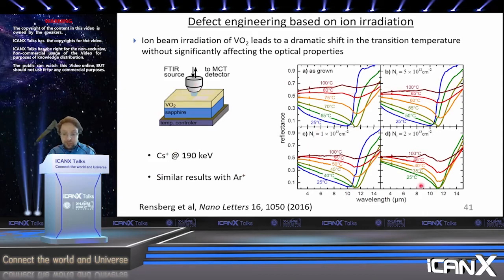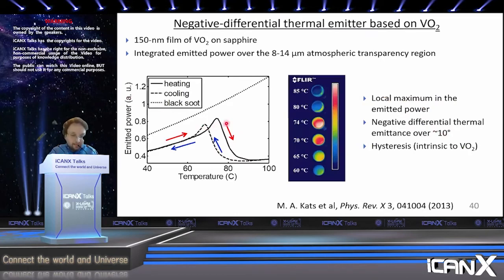And that doesn't change the optical properties too much, but it does change the transition temperature a lot. And so we can then move around the peak and the region where you have this negative differential effect on this plot. So we thought that was a compelling method using ion beams.